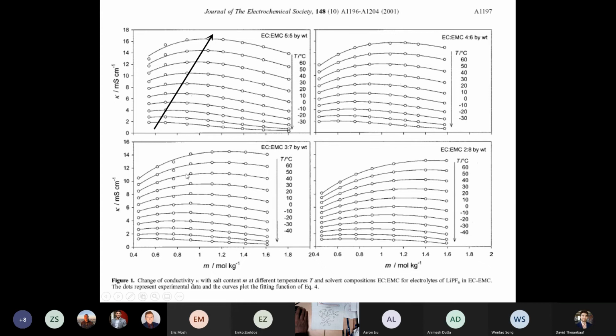So they measured, this is a lot of work, by the way. Eric Logan can tell you this is a lot of work. You have to mix up all these solutions. This is EC/EMC 3 to 7 with different concentrations of LiPF6. And then you have to measure conductivity at all these temperatures. And then you plot this graph. And then you mix up a whole bunch of other electrolyte solutions with EC/EMC 5 to 5, 4 to 6, and 2 to 8.